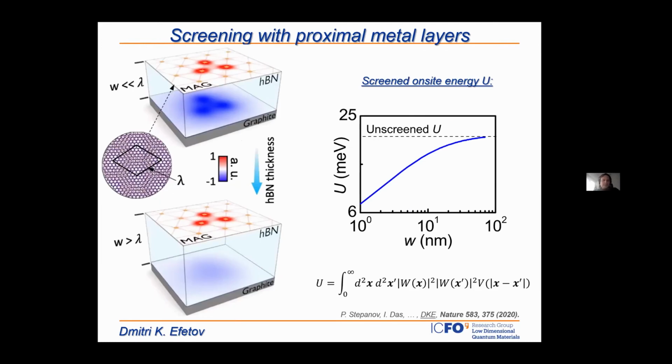In particular, talking about the dielectric environment, we realized that a crucial ingredient here could be this metallic graphite gate, which is very close by to our twisted bilayer graphene. We collaborated with Dmitri Efetov, who calculated for us the critical length between this graphite gate and the magic angle graphene for screening charges in the graphite to strongly affect the interactions in the magic graphene. We found that the length scale of the problem is similar to the size of the unit cell in magic graphene.